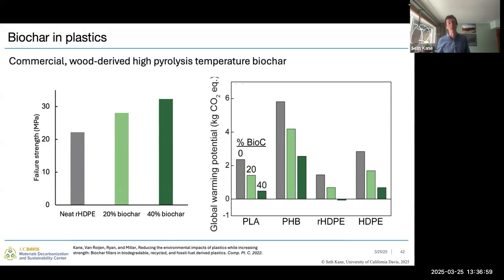Looking at introducing 20 or 40% of a commercially available wood-derived biochar into high-density polyethylene on the left, and then a couple of biodegradable plastics, recycled high-density polyethylene, and primary high-density polyethylene on the right. And so we can see that in that recycled high-density polyethylene, we see an increase in strength with the introduction of biochar. This is a result of mechanical interlocking between the porous structure of the biochar, as well as some strengthening mechanisms that are similar to what we see in carbon-derived additives for plastics, such as carbon black.